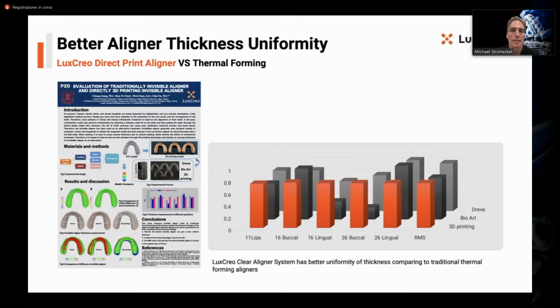This is a study that was done with the university where they were comparing thermoforming thicknesses to direct print. So we did a series of treatments and manufacturing, and you can see that with direct print, you can control the thickness very, very well. And we have single thickness, like I said, gradient thickness, and occlusal thinning, so you can improve the bite but still maintain the thickness everywhere else. And then you can do a full free-form multi-thickness using our machine learning. But when you look at single thickness, we're doing single thickness everywhere. This is actually very challenging, to be able to print and have your thickness be consistent time and time again.